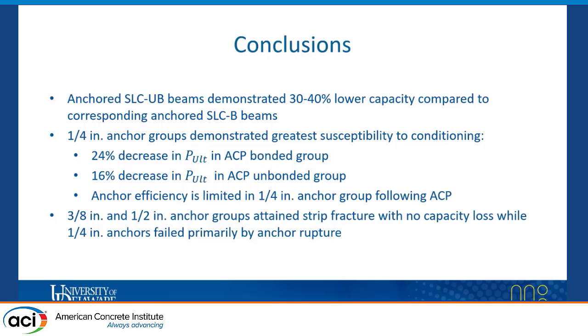To conclude, as mentioned, the anchored SLC unbonded beams demonstrated a lower ultimate capacity amounting to about 30 to 40% compared to their corresponding anchored SLC beams. The quarter-inch anchor group demonstrated the most susceptibility to the effects of hygrothermal conditioning, as there is a decrease in ultimate capacity of 24% for the bonded group and a decrease in ultimate capacity of 16% for the unbonded group. In addition, the anchor efficiency decreased following conditioning.